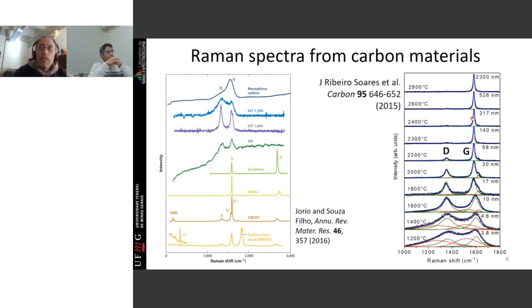And one interesting aspect here is, okay, here again, this peak that you see in the Raman spectrum is the G peak. But you have one peak appearing here that only appears when you have defects on graphene. And if you increase the amount of defects, you increase the contribution to this peak in the spectrum. And with this information, you can characterize the amorphization of a graphene sheet, okay? This has been very largely used in all the industry that utilizes carbon as a material, okay?